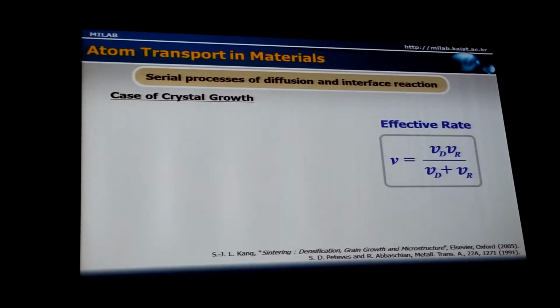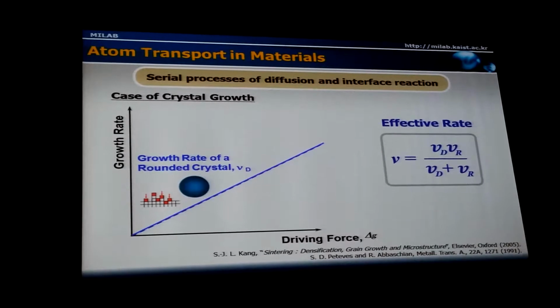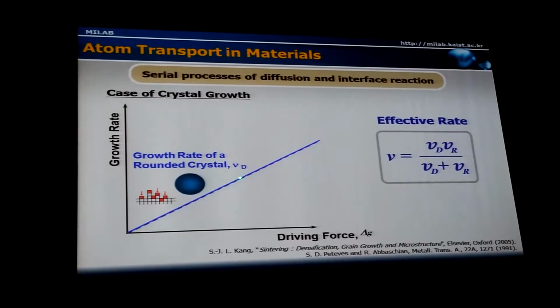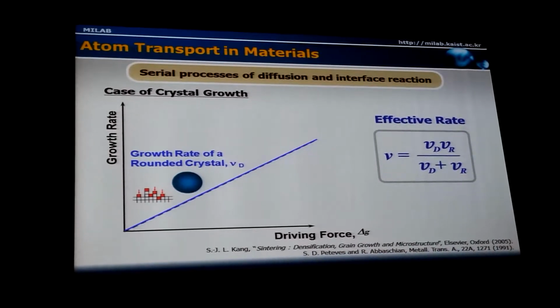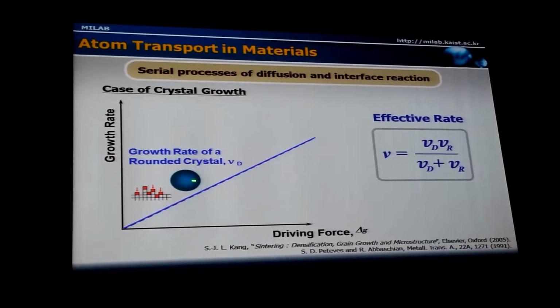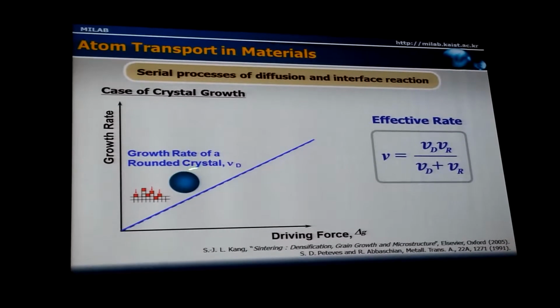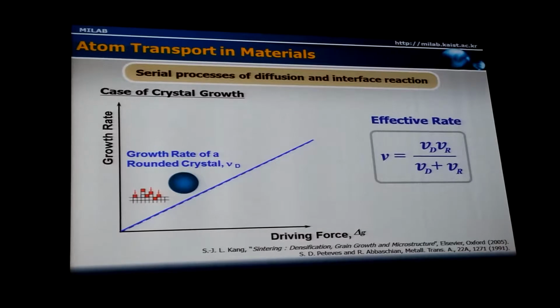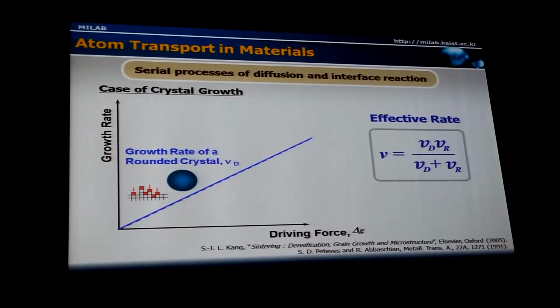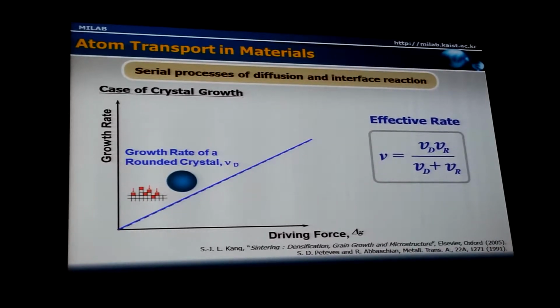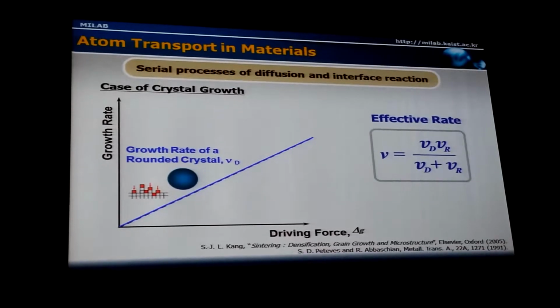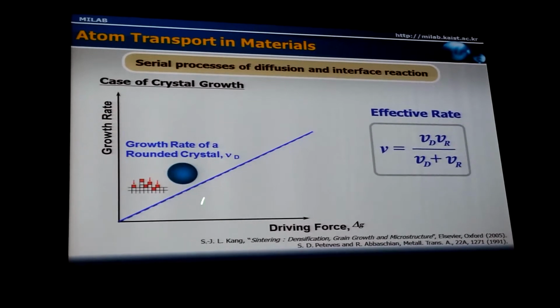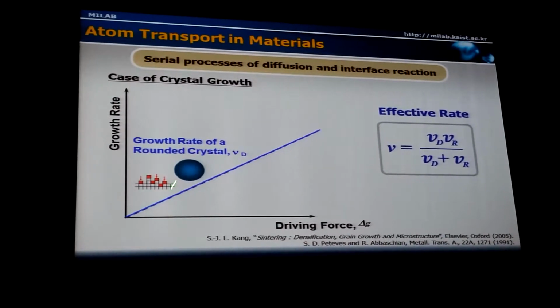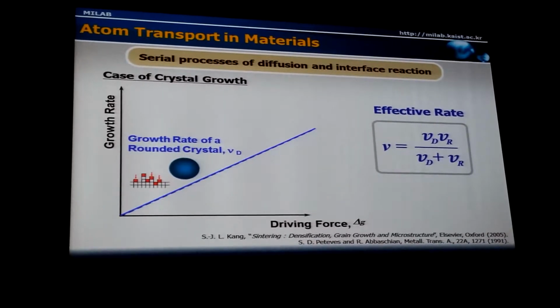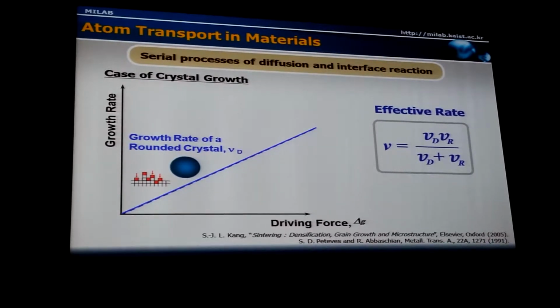So in the case of crystal growth, when the crystal shape is rounded with an infinite number of surface atomic defects, the attachment of atoms, meaning the interface reaction kinetics, is much faster than the diffusion rate. Therefore, for the growth of such a round spherical crystal, the interface reaction is faster, so diffusion will govern the overall kinetics.